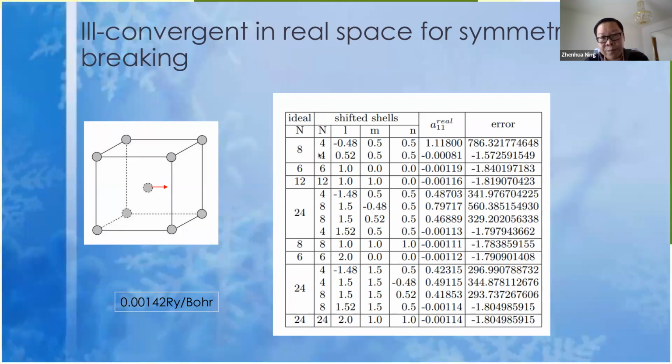Because of the symmetry breaking, the shell is split into 2 subshells, 4 atoms in each subshell. Similar thing to the second shell, it is split into 4 subshells, and the seventh shell is broken as well. Because of symmetry breaking, the A11 term appears. This term should be welcomed since it contributes to the force calculation.